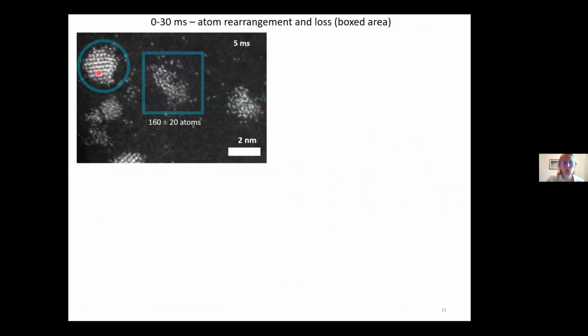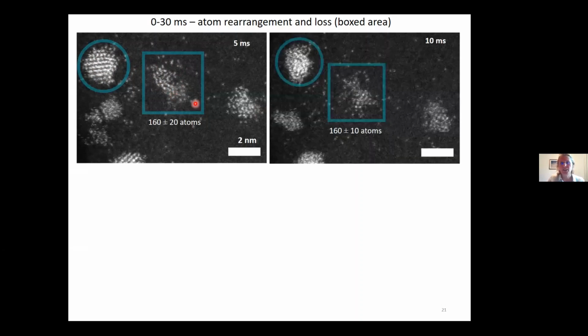So this is an example of a crystalline nanoparticle. You can see how the atoms are formed into these nice crystalline lines. This is one of our atom clusters, right? So it's got no preferred crystallographic orientation yet. This is at 5 milliseconds. We've counted the number of atoms in here. If we then click to 10 milliseconds, you see it still contains the same number of atoms, but it's starting to rearrange itself again.